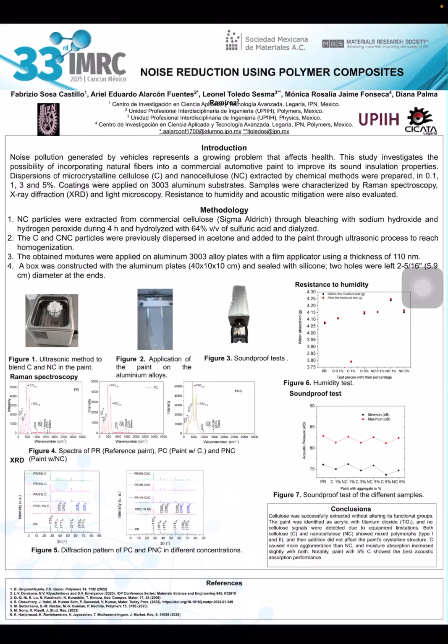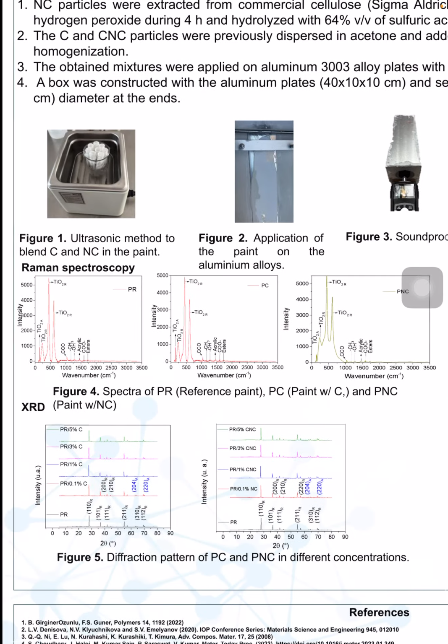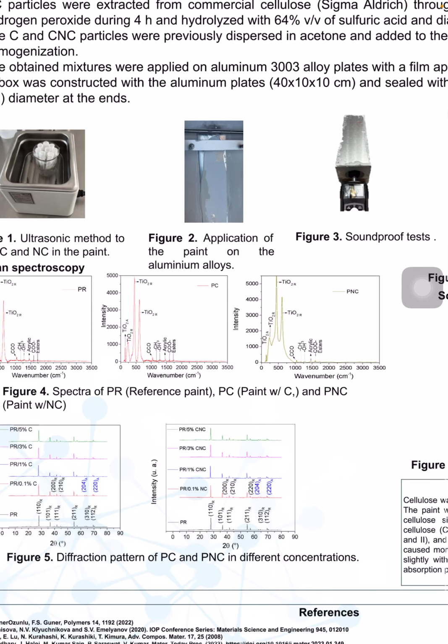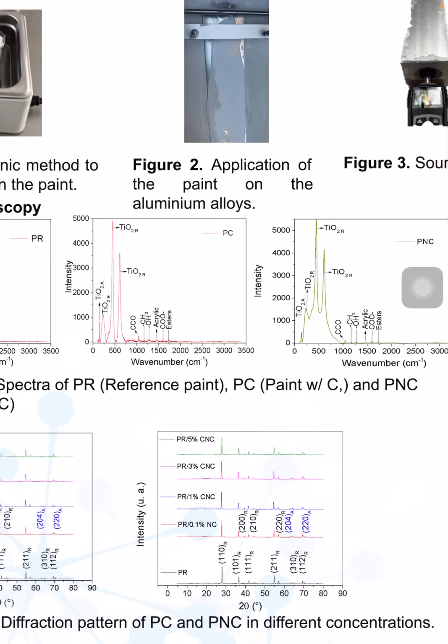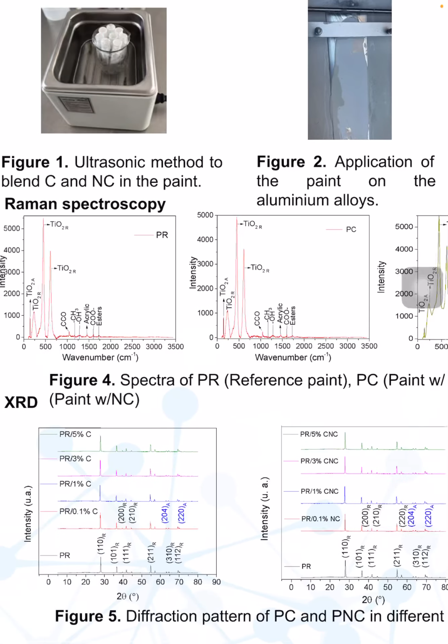But before that, we took the paint with different concentrations of C and NC and performed Raman, XRD, and humidity tests. In chemical structure, Raman and XRD confirmed that adding the cellulose didn't alter the main chemical composition of the acrylic paint. Titanium dioxide, already present in the paint as a pigment, remained unchanged. We can see that adding cellulose and nanocellulose, we don't see any change compared to the reference paint that is here.